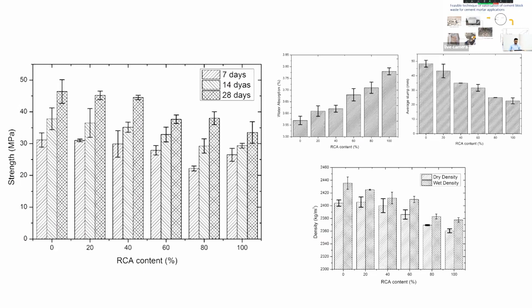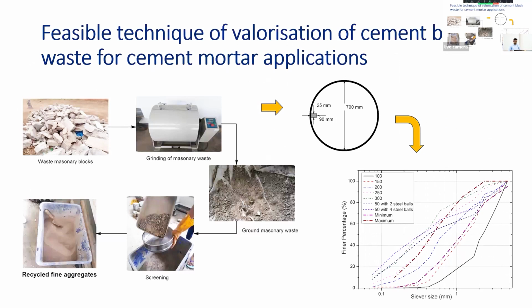So the second one is another technique that we can use to produce fine aggregate using waste cement blocks. In this study, what they have done is they have used a steel drum with small notches. As you can see in the cross sections, they have put broken cement blocks into this steel drum, and they have rotated it in different ways. They changed the number of cycles. They have added different sizes of steel balls in order to increase the speed. Based on that, as you can see in the particle size distributions, we can have a variation of the particle size distribution based on the requirements.